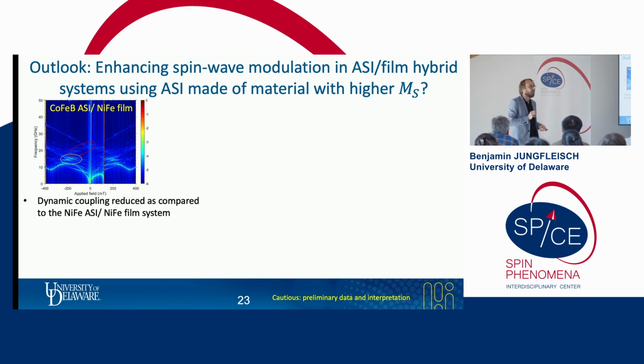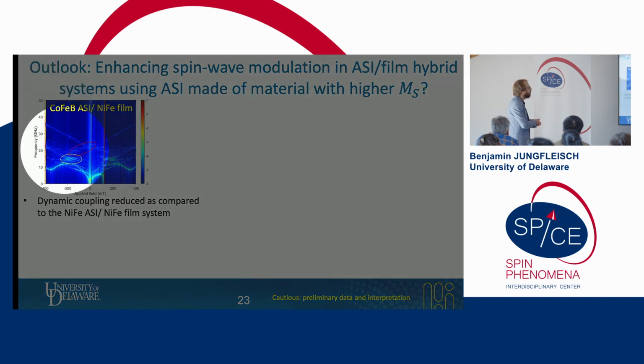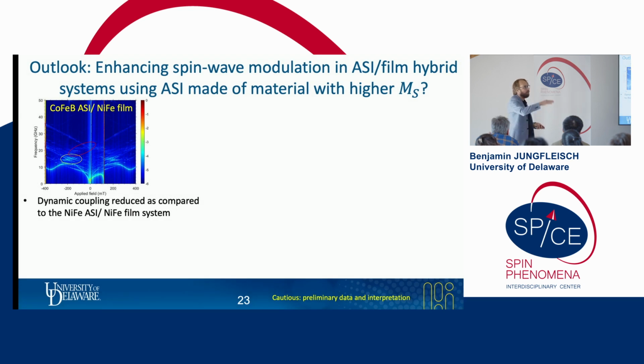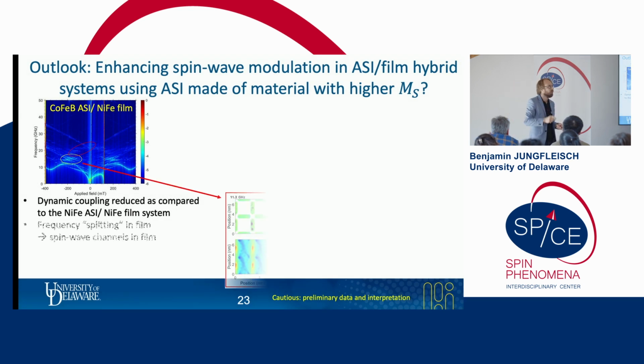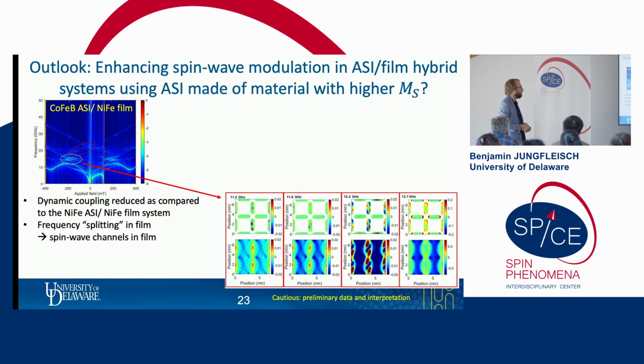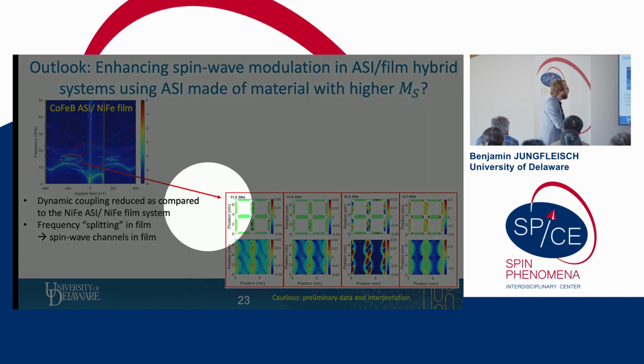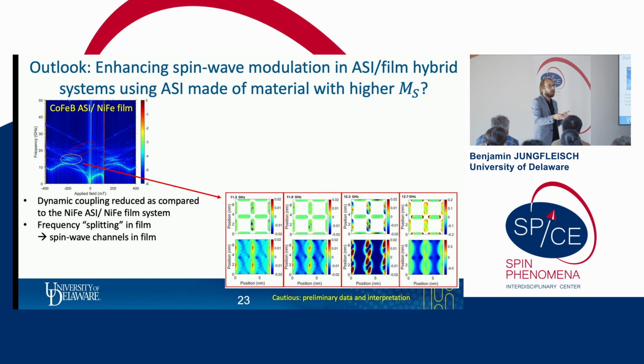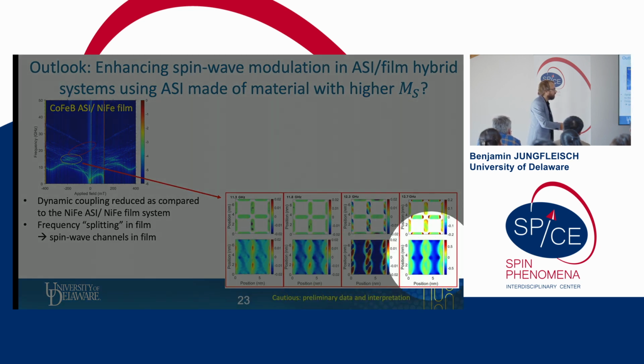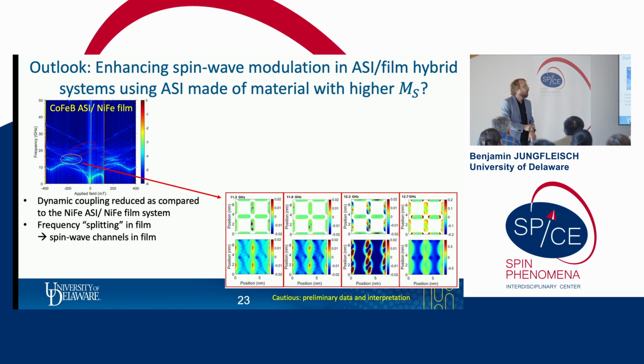So first of all, what we see, or at least tentatively what we see, is that the dynamic coupling is reduced as compared to the all-permalloy system. And then we noticed something interesting. There are some modes which are running basically parallel to each other, and they have the same frequency separation. So I'm showing here first the film underlayer, where we see a frequency splitting in the film. You can see this is 11.3 gigahertz, 11.8, 12.3. So they are all approximately 0.5 gigahertz apart. And this leads to spin wave channels in the underlayer, as you can clearly see. So it's independent of the frequency.